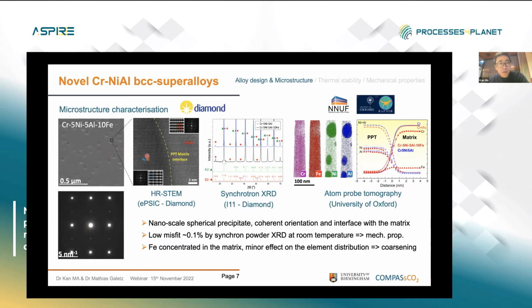And also, in fact, this novel material, chromium, is quite a nascent class of material, and this material has a wide appeal for the community, so we have created a wide collaboration with other external partners. For example, we have performed high-resolution TEM observation on the interface, which is shown by this micrograph, and shows the interface is highly coherent between the precipitate and the matrix. This observation was performed at ePSIC in Diamond.